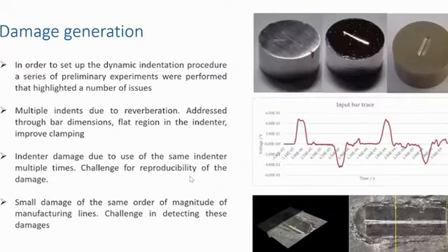So we start the setup. We started developing this dynamic indentation procedure, taking care of the setup with many preliminary specimens. We first wanted to understand if the smaller damage was detectable, since it was almost the same order of magnitude of the manufacturing lines, and we verified that it was possible.